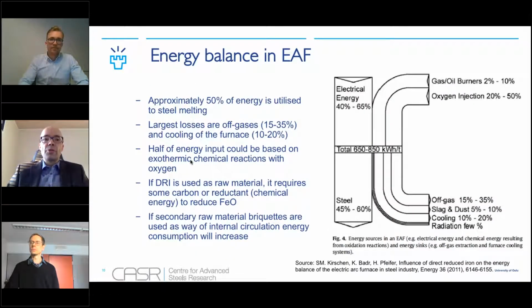If you look at the energy balance of electric arc furnace, we see that approximately 50% of energy is utilized for steel melting, and the off gases and cooling of the furnace are the largest losses, having together nearly half of the energy used by these two ways.